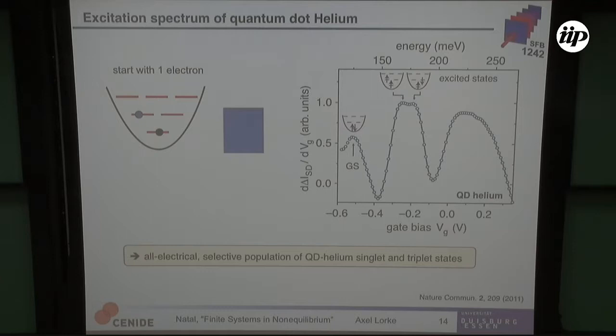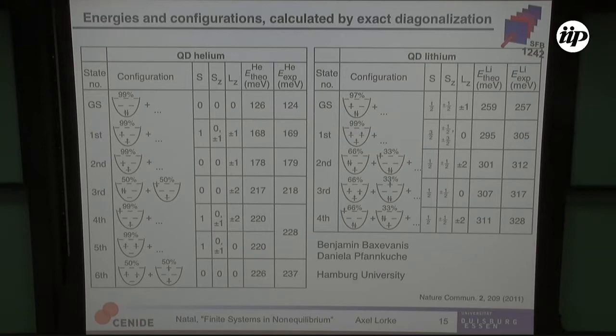So here we have a direct approach to the exchange interaction. So it's an all electrical way to selectively populate quantum dot helium in the singlet and the triplet states. We work together with theorists from Hamburg University who did a numerically exact diagonalization of the two-dimensional harmonic oscillator, and the theoretically obtained energies and the experimentally determined energies worked so well, not just for the quantum dot helium, but also for the quantum dot lithium, that it gave us confidence that this assignment was really correct.